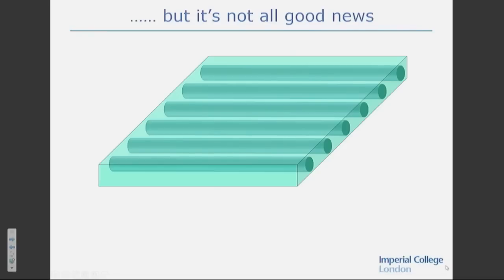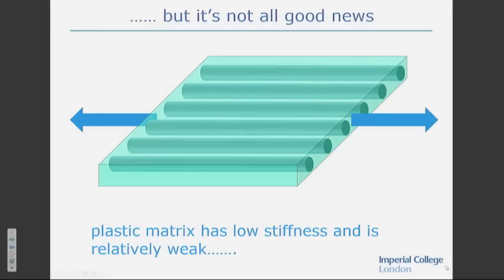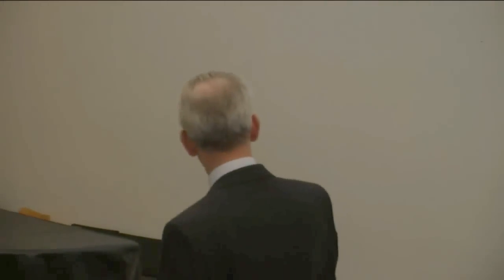And we've got to go back and look at our description of the carbon fiber reinforced plastic matrix. Here it is, sitting here, carbon fibers and the plastic matrix. The bad news is that this plastic matrix has low stiffness, but more importantly, it's got low strength compared to those fibers. So if we're putting load on in the fiber direction, like those blue arrows, everything's fine. But if we put load in the transverse direction, we'll find we won't be able to put much on before it'll fail.